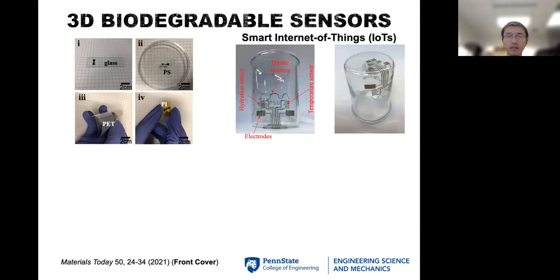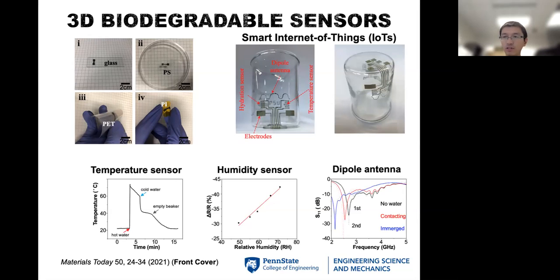And we can also do this on a 3D geometry with the kirigami design of the carrier substrate. We will be able to transfer the zinc pattern onto the 3D glass beaker. And we're able to create the hydration sensor electrode for electrophysiological signal detection, dipole antenna, temperature sensor. And the signal is very high quality to allow us to detect, for example, cold water, hot water, empty of the beaker. And you can detect the relative humidity of the ambient environment. And the dipole antenna can also transmit the data to the outside.